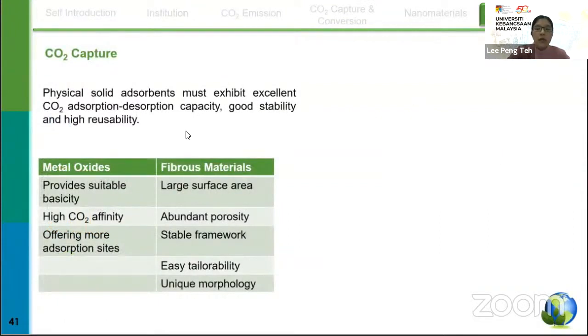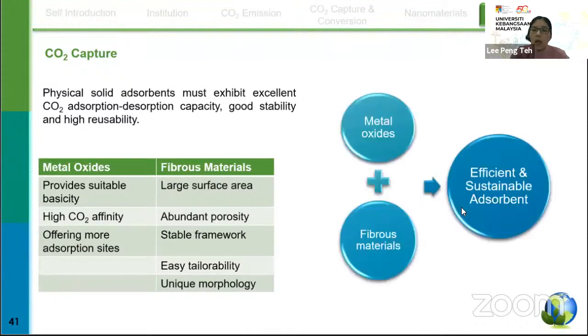So all these types of adsorbent, we call physical solid adsorbents. These physical solid adsorbents exhibit excellent CO2 adsorption-desorption capacity, good stability, and high reusability. The metal oxide provides a suitable basicity because, as I mentioned earlier, CO2 is basically mildly acidic. So the metal oxide can form a chemical bond with the CO2 and it has a high CO2 affinity. It will offer more adsorption sites for CO2 adsorption, while the fibrous material acts as the support of our materials, because fibrous material has a large surface area, abundant porosity, stable framework, is easy to tailor, and has unique morphologies. I believe that by combining both metal oxide and fibrous material, we can develop very efficient and sustainable adsorbents.